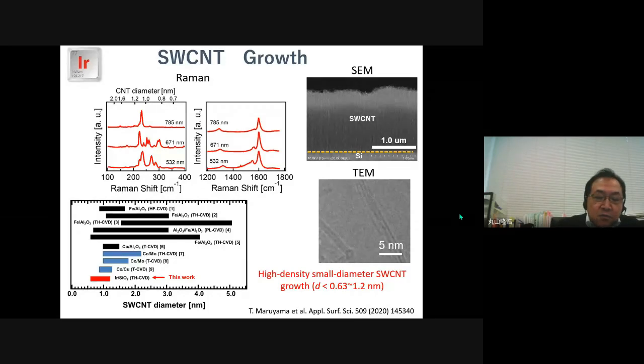The lower figure shows the diameter distributions of single-wall carbon nanotubes grown from iron, cobalt, and iridium catalysts. Previously, vertically aligned single-wall carbon nanotubes were grown only from iron and cobalt catalysts. However, the diameters of grown nanotubes were distributed from 1.0 to 2 or 4 nanometers. In contrast, our results showed iridium catalysts are effective to grow small diameter single-wall carbon nanotubes with high efficiency. Next slide, please.